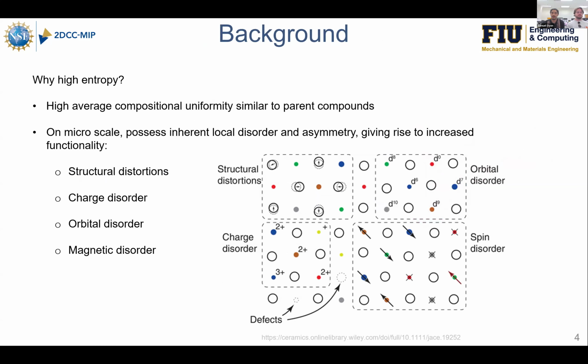And while we were looking at the parent compounds, our point of interest for the RSVP during the summer was introducing high entropy into these parent compounds. The reason why we wanted to do high entropy is that they have, on average, higher compositional uniformity, similar to their parent compounds. And because there's a lot more elements that we're introducing to the crystal structure, there's a lot of local inherent disorders and asymmetries, which allow for a bit more fine tuning of certain parameters.